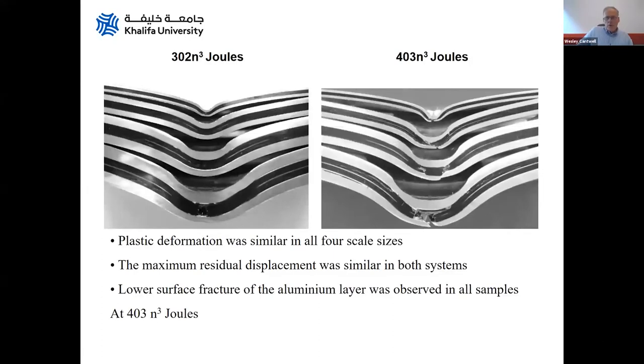But the proof of the pudding really is in sectioning the samples, looking at the damage within them and comparing them. So here we have two different impact energies, 302 N cubed joules and 403 N cubed joules. If you take these sections on the left-hand side, this is our N equals one sample subjected to 302 joules. It's got a little bit of damage here in the composite. You can see some thinning here in the aluminium layers as well. And if you look at the other scale sizes, you see similar types of damage there. You can see this thinning here in the aluminium. And you can even see a small damage there in the N equals quarter sample that's been subjected to an impact energy of only 5 joules, but still this 302 N cubed joules.